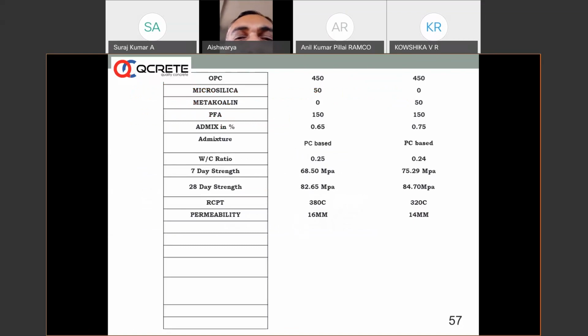Again, using metakaolin and microsilica, the RCPT value, which is measured as per ASTM C1202, in the columns represented here, 380 coulomb and 320 coulomb columns, shows that the concretes are excellent and extraordinary, because when the value falls below 500, that kind of concrete is said to be one of the best concretes as far as chloride resistance is concerned.